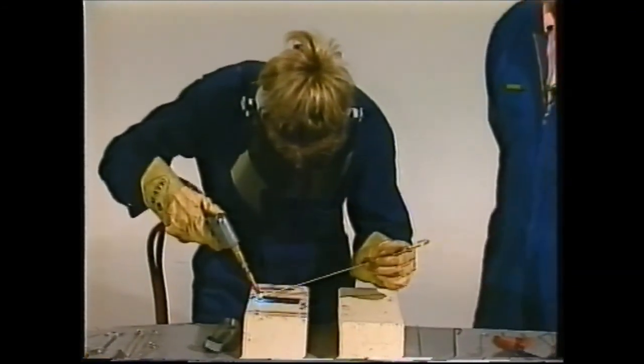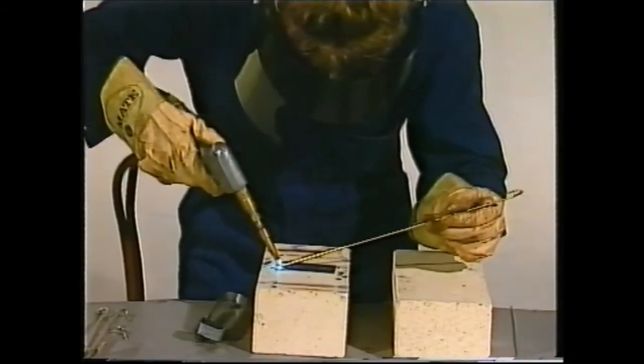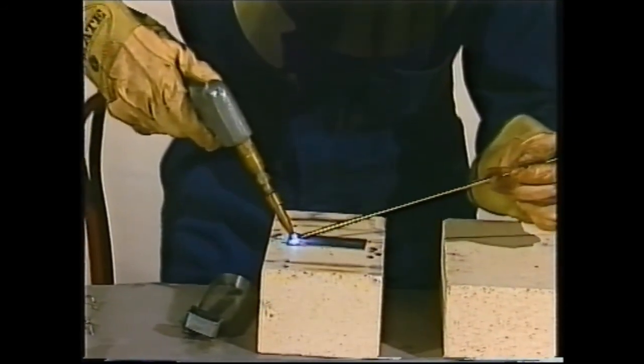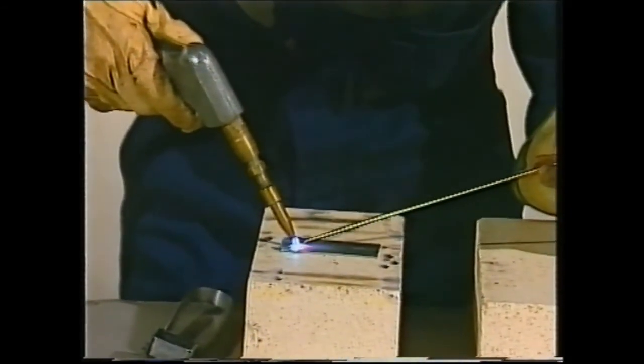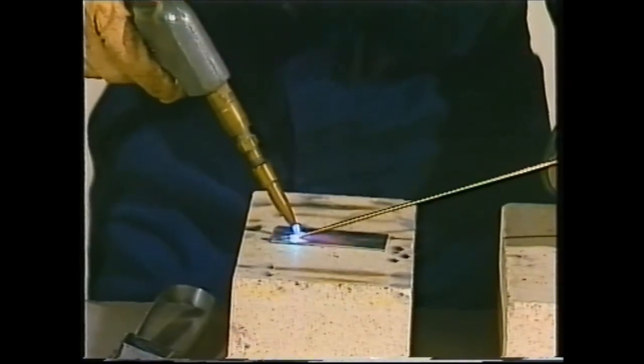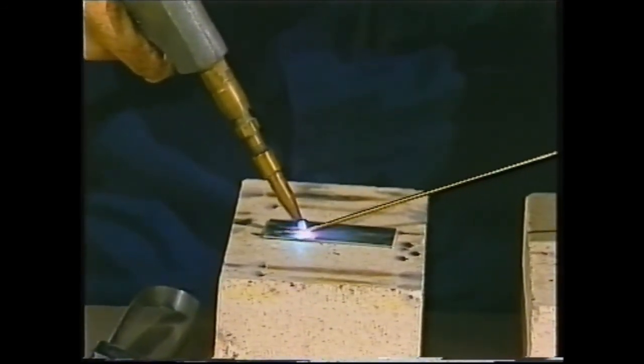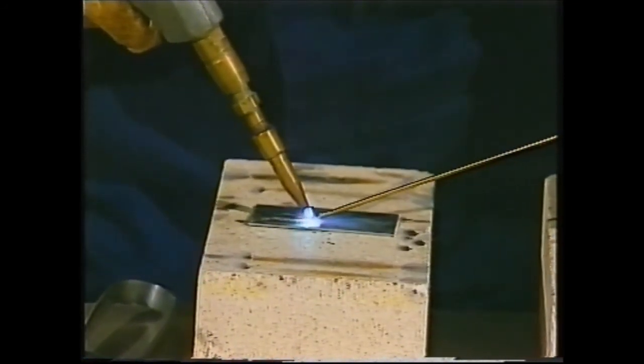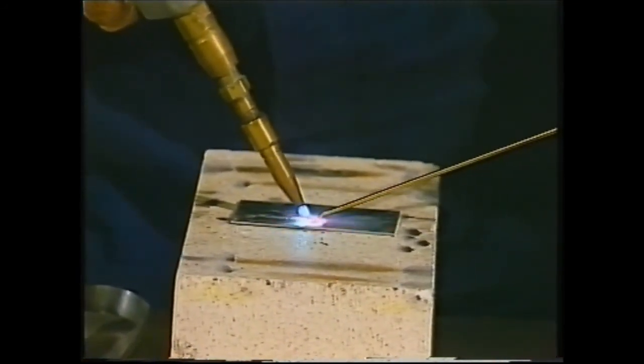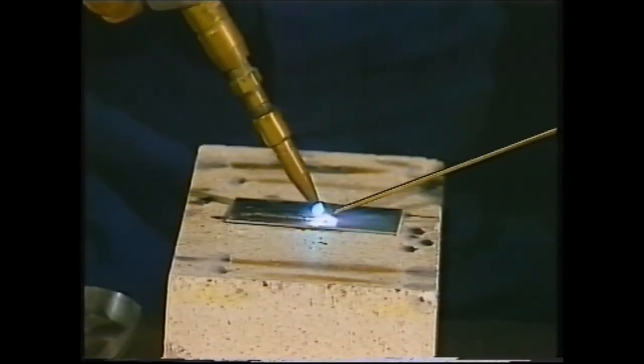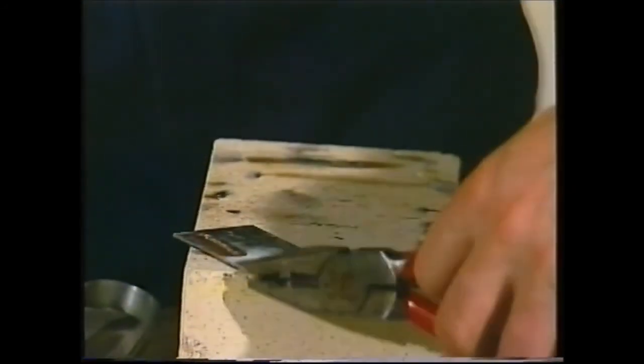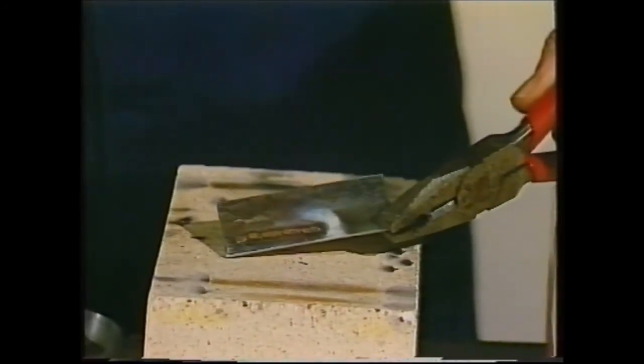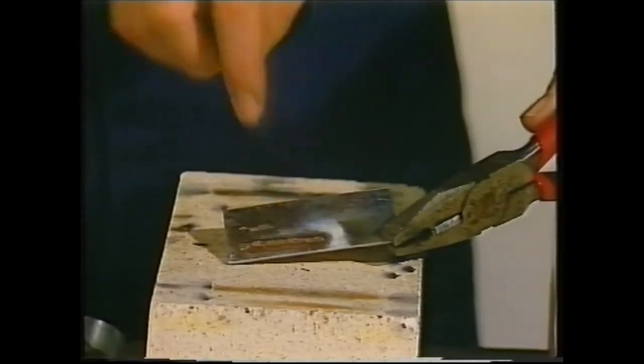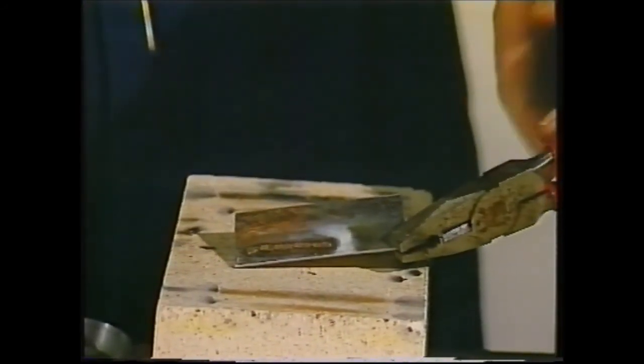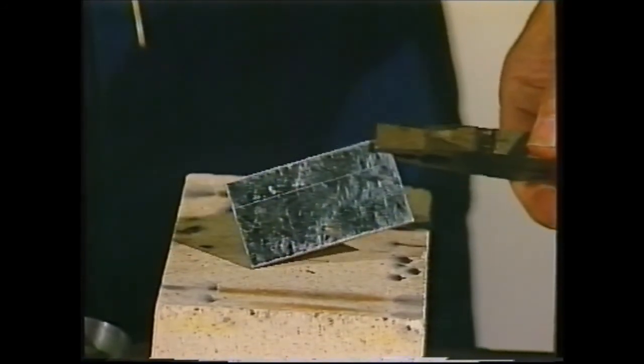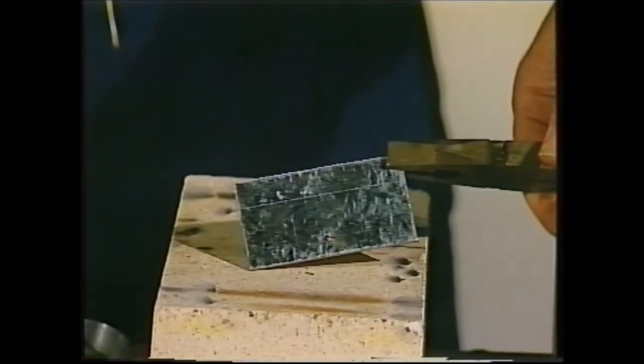but most importantly, the torch will braze into galvanised material without even burning the galvanising off. Fantastic ability for people such as sheet metal workers, particularly with air conditioning ducting and things like that. The zinc actually will separate under the flame, and it comes back around the edges and really seals in tight on the bronze filler rod. That's lovely, thanks, Lynn. Now you can see there how it has really sealed in tightly around the edges. You can actually see the rim of the galvanised material, the zinc, but I'll turn it over and have a look at the fact that it just has not burned any of the galvanised coating off, even off the rear.